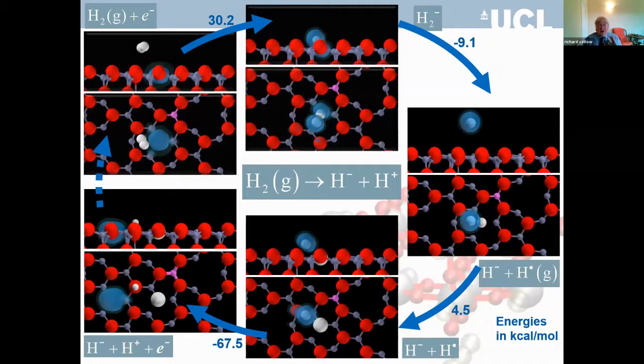I just want to look very briefly at two key processes, and that is the hydrogen dissociation and the CO2 activation. Now, zinc oxide is an n-type semiconductor, so there are trapped electrons on the surface. Hydrogen can approach that surface. The trapped electron is the big blue feature indicated on this graphics. It reacts with hydrogen. This is computationally deduced to form an H2 minus ion.